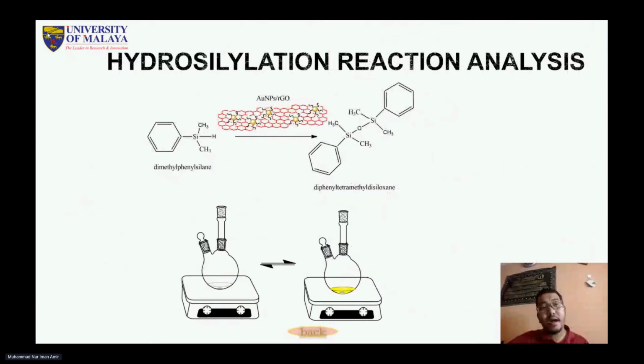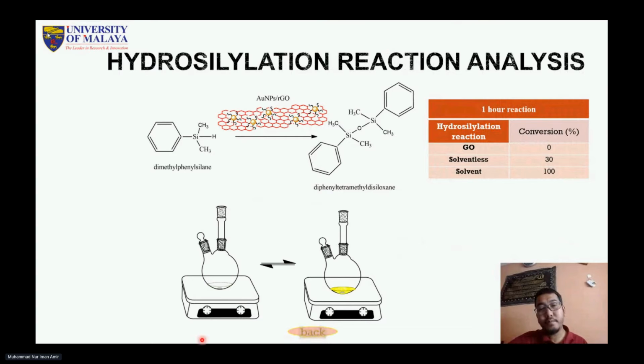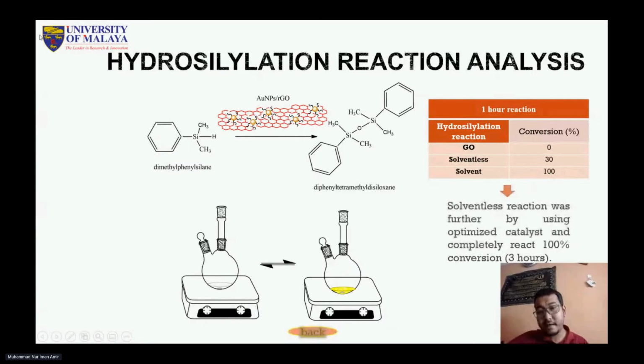We further analyzed the hydrosilylation reaction within 1 hour, and we are doing a comparison between the GO material alone and the catalyst that undergoes solventless and solvent reaction. We found that the GO alone has no reactivity due to being an inactive material, while the solventless reaction can only give 30% conversion, and the highest, with 100% reactivity, is done by the solvent reaction. Next, the solventless reaction was carried out further using the optimized catalyst, and it completely reacted, 100% conversion, within 3 hours.